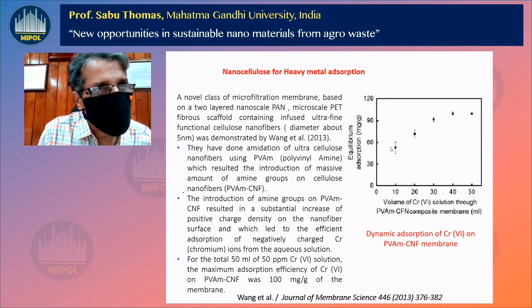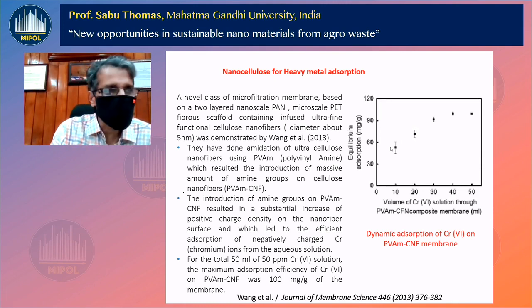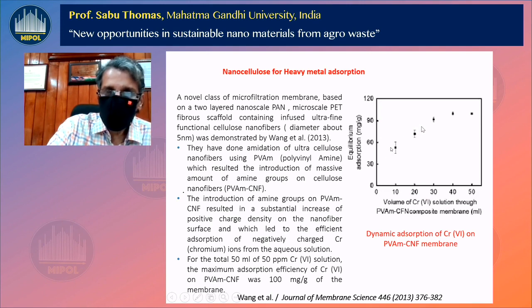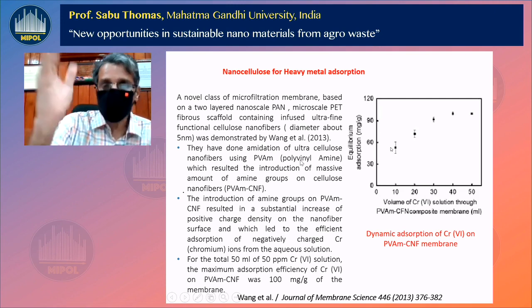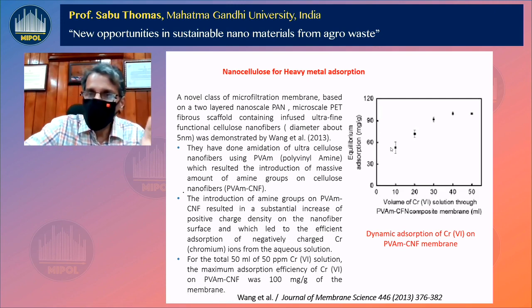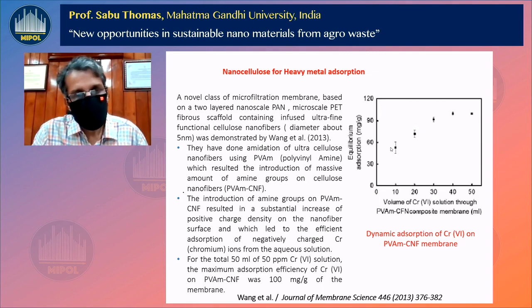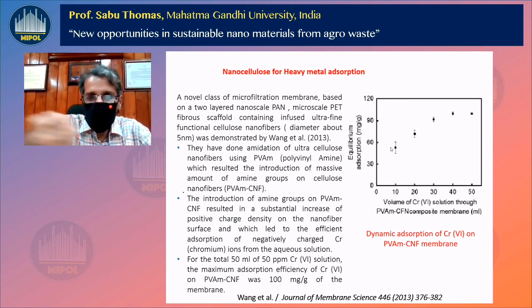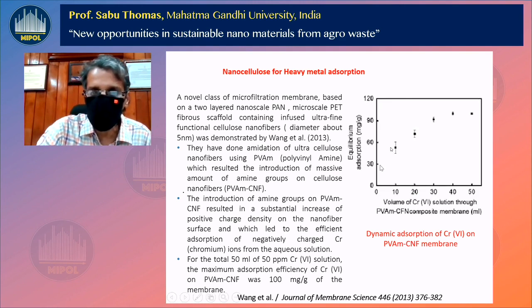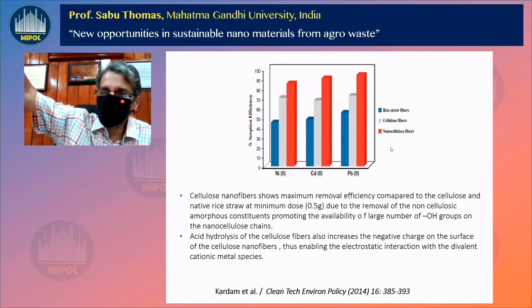Let me now show you removal of heavy metals. Look at India, the northeastern part of India, where we have lots of heavy metal in drinking water. And people use different types of filters to remove that. You can make use of nanocellulose to remove heavy metals. Look at this chromium 6. If you want to remove chromium 6, which is negatively charged, you do a small chemistry. You react nanocellulose with polyvinylamine. When you react it with polyvinylamine, you make the nanocellulose surface electropositive. You use a lot of amino groups. And the negatively charged chromium 6 will be captured by electrostatic interaction. You can look at this. You see the trapping of chromium 6. You can remove nickel, you can remove cadmium, you can remove lead.